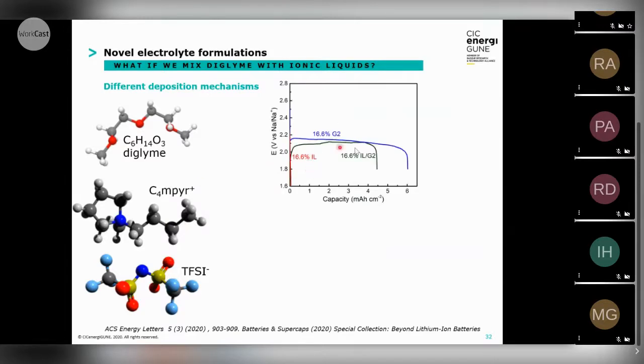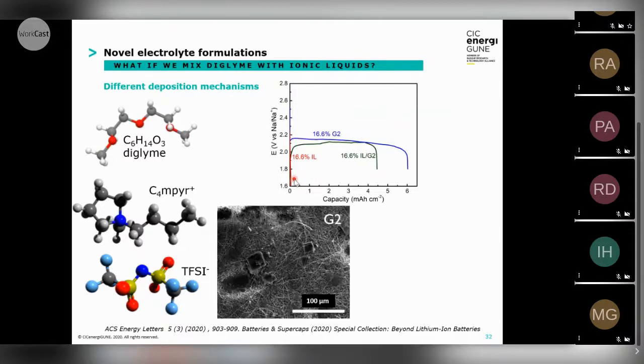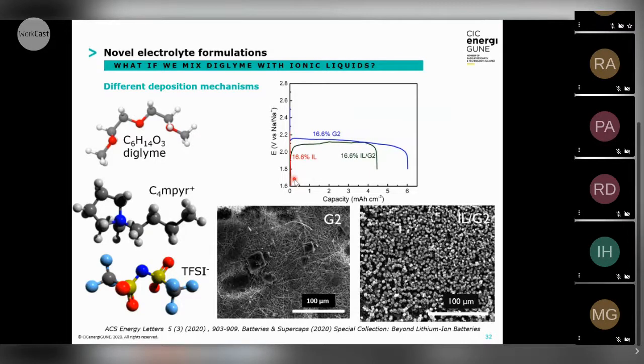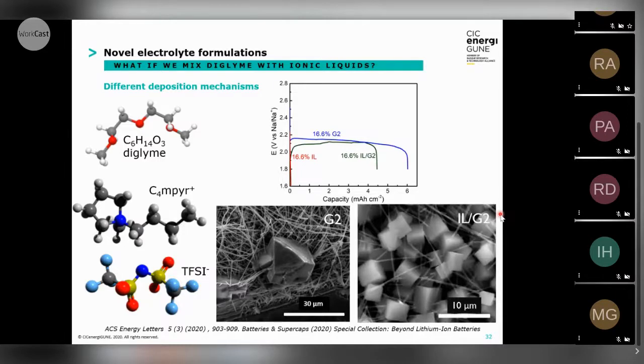So here we have a discharge also in a commercial carbon cathode with sodium metal, and we see that the glyme capacity is higher. Then we have the mixture, which is also quite good, and with the ionic liquid alone, it's not able to discharge, probably due to the viscosity, because it's really viscous and the oxygen solubility is low. Surprisingly, in the case of glyme, you can see these cubes randomly oriented on the surface, with different sizes. But in this mixture, you can see a really homogeneous distribution of these cubes along the surface, meaning that something has changed just by incorporating this ionic liquid into the glyme. The cubes are smaller and uniformly distributed.